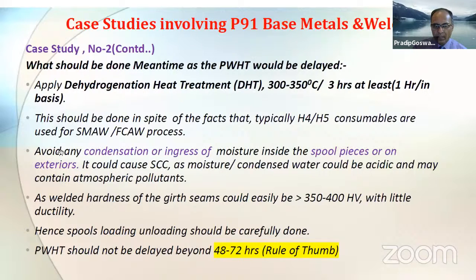Now, many of us may not be aware of the consequences of any kind of condensation or moisture on these steels which are not post-weld heat treated. But industry experience in North America has shared delayed post-weld heat treatment, followed by the ingress of moisture or any condensation on the steel, as the root cause of so-called SCC, or stress corrosion cracking, for these. There have been some case studies or interesting findings on delaying the post-weld heat treatment without taking much precaution, typically in a humid climate.